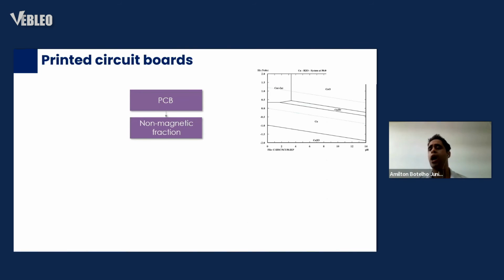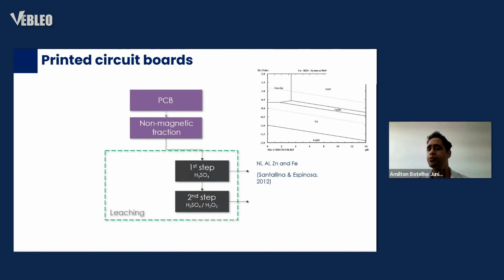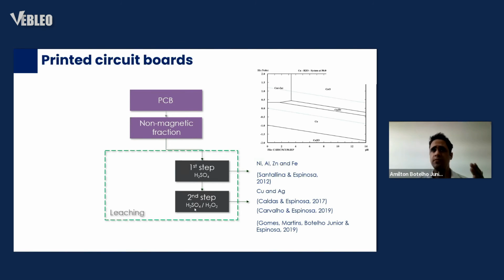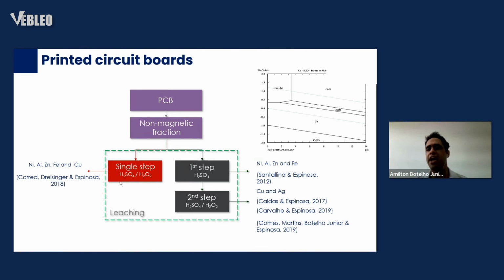So I have an example here of how to recycle PCBs. After the physical procedure, the non-magnetic fraction goes through the leaching procedure that can occur in two steps. First, we use sulfuric acid to remove nickel, aluminum, zinc, and iron. And secondly, sulfuric acid and hydrogen peroxide to obtain copper and silver. Or you can do a single step using sulfuric acid and hydrogen peroxide to obtain all those elements.